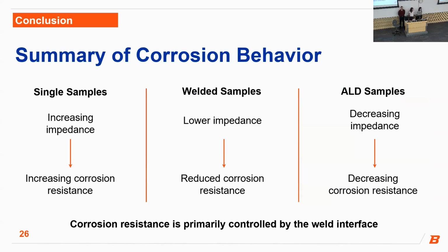So overall, our results demonstrate that the weld interface is the dominant factor in controlling corrosion behavior in additively manufactured to wrought stainless steel systems. Our welded samples consistently exhibited lower impedance compared to our single samples, and while surface finishing improved corrosion resistance, it did not eliminate the influence of the weld. Our ALD-coated samples showed an early decrease in impedance and visible corrosion. However, due to limited time, we cannot make any definitive conclusions about long-term mitigation. But overall, these findings confirm that the weld interface is the most susceptible region to degradation and governs corrosion behavior.